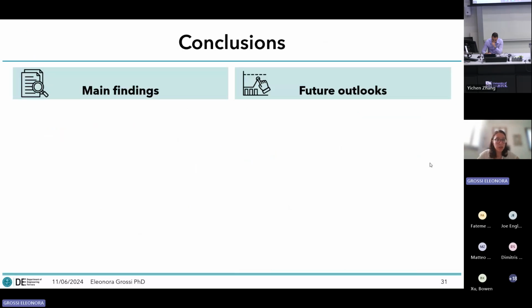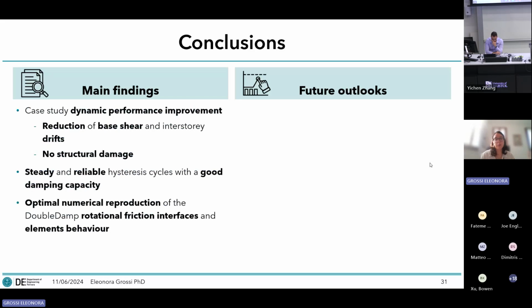So for the conclusion, I can say that Double Damp can significantly improve the dynamic performance of an existing structure, reducing the base shear and interstory drift, avoiding any structural damage. The mechanical tests show me that its hysteresis cycles are quite steady and reliable and have a good damping capacity, both in the monodirectional and bidirectional test. And finally, the numerical model that I implemented well represents the behavior of the device, especially for the rotational friction interface, and is quite useful to develop a virtual lab tool for further investigations.